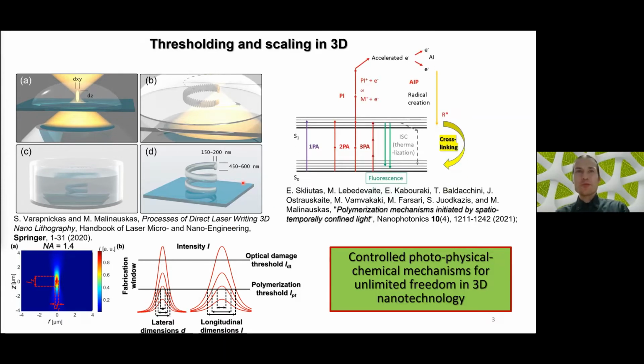Since it's not the topic of today's talk, I won't go deeper into the details of what mechanisms can be involved. It can be one photon, it can be 3 photon, typically it's a 2 photon process, followed by photoionization, which induces avalanche ionization. But nevertheless, all of these processes can be optimized, whether single ones or in combination, to induce localized chemical reactions, which will result in cross-linking of the material. It means the monomer will be turned into polymer, or more simply said, from liquid, we make hard details,